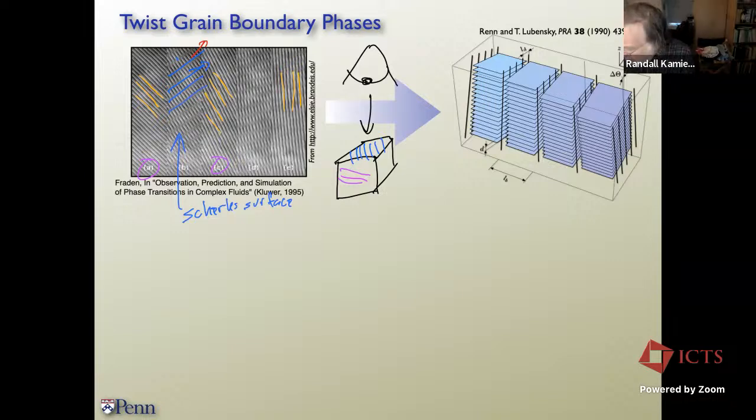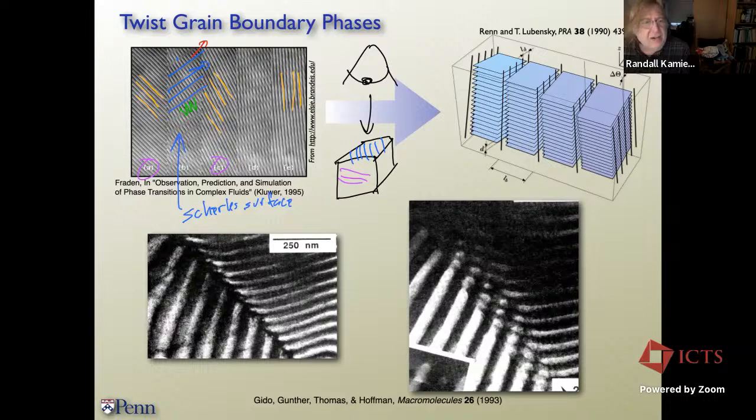The helicoids, as you go around them, let's see if we can do this. As you go around them, so you come this way and then you go up, over, up, over, up, over. So you're actually going and rotating around that line. And so here's a physical realization of the helicoids and Scherk's first surface, all in this quite simple system. And here you can see, using electron microscopy, you can actually see regions of this in the diblocks. These are diblocks.